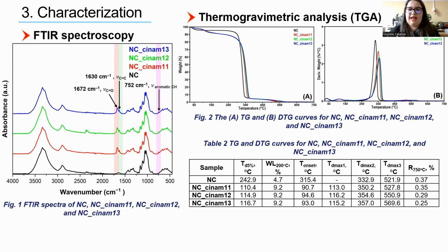The thermogravimetric analysis indicated that the loading of cinnamaldehyde in the nanocellulose sponges led to a decrease in the thermal stability of the nanocellulose, which was notable by a new degradation step that appeared between 70 and 200 degrees Celsius. This can be attributed to the release of cinnamaldehyde from the sponges or to the thermal degradation of cinnamaldehyde, which, being a compound with a lower molecular weight than nanocellulose, suffers thermal degradation before nanocellulose.